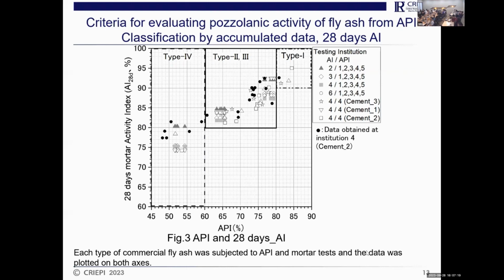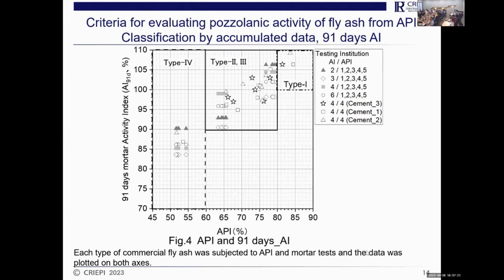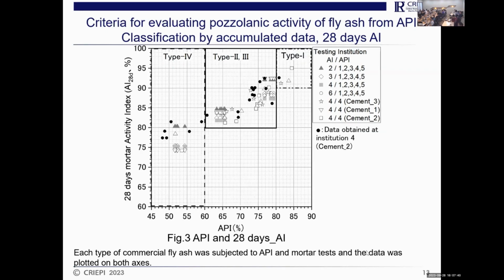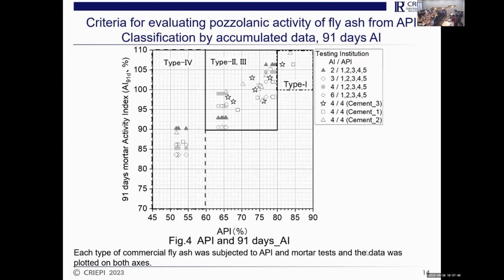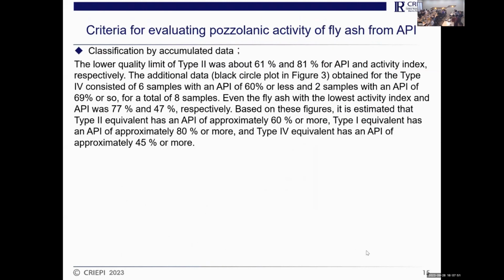As shown in those figures, we only need to operate the API method one time. So we can determine the one API, and we can determine both mortar activity indexes, 28 days and 91 days data. It's very simple.